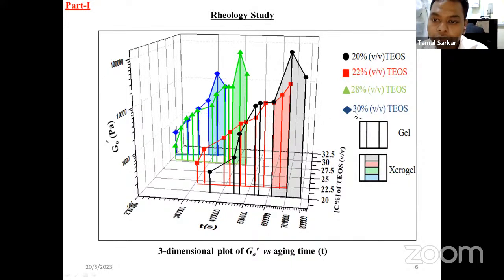What I wanted to show is that as I keep on increasing the concentration of TEOS, the gelation and xerogelation time kept on decreasing. We could see black is for 20% TEOS, and from here to here, that means from sol to gel state, it takes longer time than the 30% TEOS case.